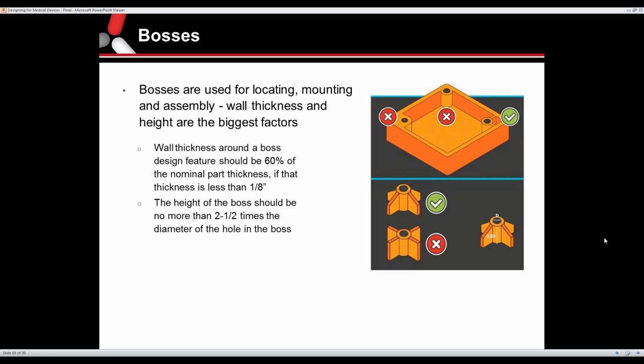Not trying to put them right in the corner where you have a lot of material. It's just going to create sink and just not a good surface finish on the exterior of the part. And the example to the right there is still going to provide you a good boss with good structure and good strength, without, as John said, creating a very thick wall area, which is going to create all sorts of issues with sink marks and so forth.